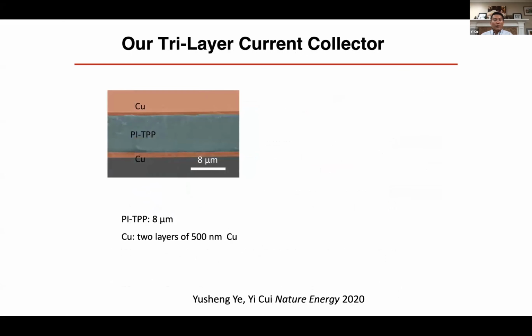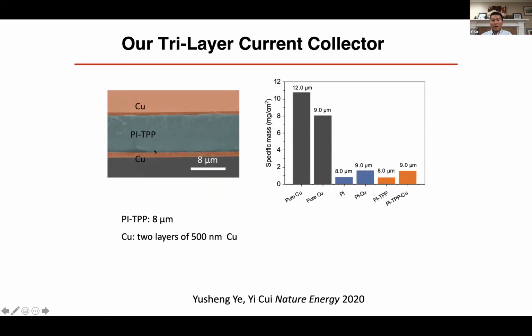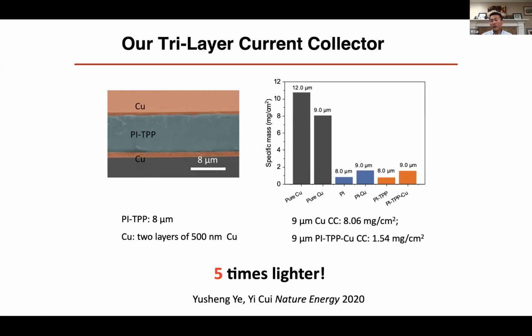For example, a current collector we made right here is a PI polymer with TPP fire retardant in there with copper coating, 500 nanometer. And we can reduce the weight per unit area. For example, 9 micron copper will get to 8 milligram per centimeter square. Now with this fire retardant plastic current collector, 9 micron, we get to less than 2 milligram per centimeter square. We have 5 times lighter current collector, right? At the same time, the embedded fire retardant makes it much safer.